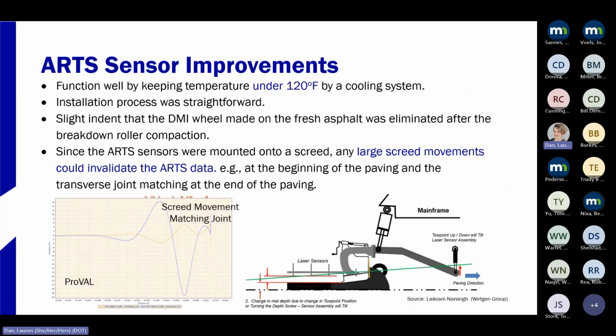So overall, we did have good success in using this setup. We were able to maintain the temperature inside the sensor below 120 degrees by cooling the system. And the installation process was also quite straightforward. Some of you might have noticed that the DMI between the two sensors was leaving a small tire indent behind the paver screed, but even that was just behind the paver screed. Once compaction is done, we couldn't even see the line caused by that.